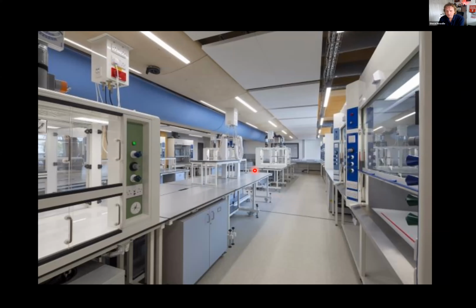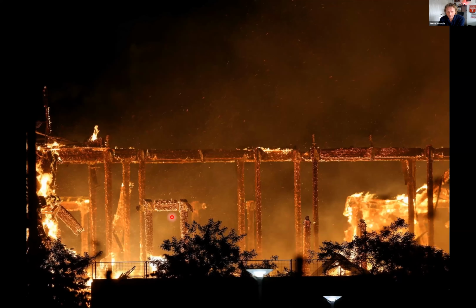But what about the fire, I hear you ask? Were you stupid to build a chemistry building out of wood? Well, all of the architects beforehand told us that this was not a problem, that wood was actually not as flammable as people would believe. And some interesting data came out of the fire. So it showed that at this point, in the middle of the fire, the substructure was still standing. And this was still standing many hours after a conventional, normal concrete building would have completely collapsed. And the fire engineers were absolutely amazed. And the reason is because these big wooden struts actually form a charcoal intumescent barrier around them that keeps them stable. And so this was much more stable than anybody would have expected it to be. So this was very positive news.